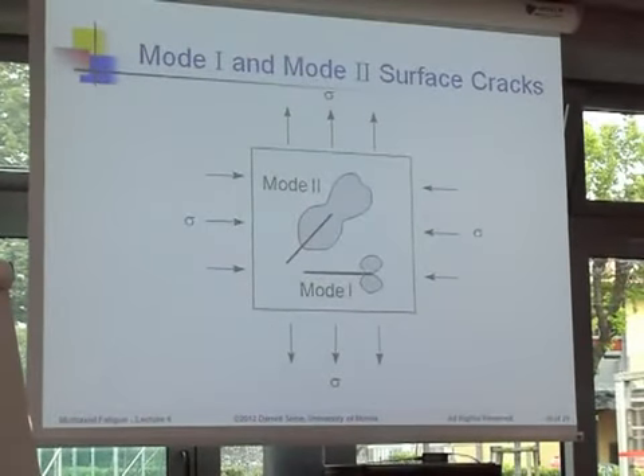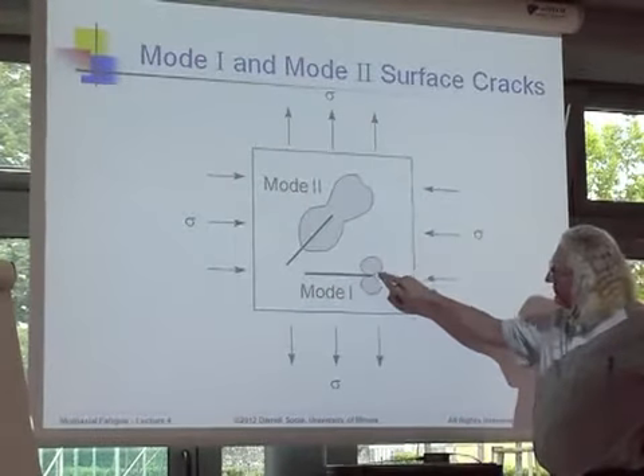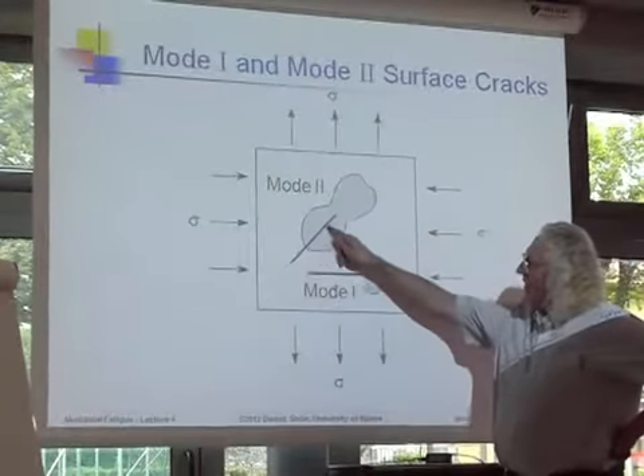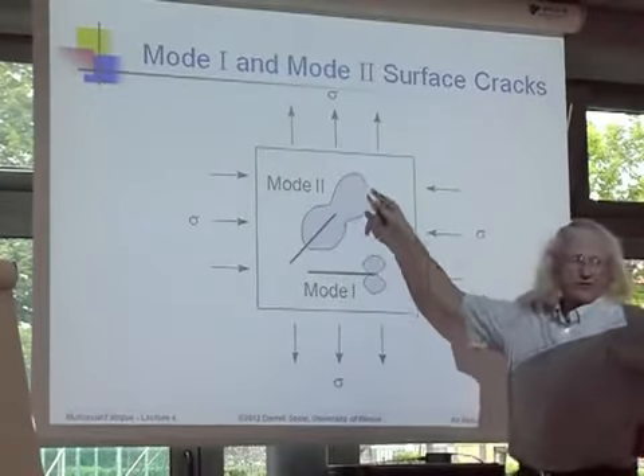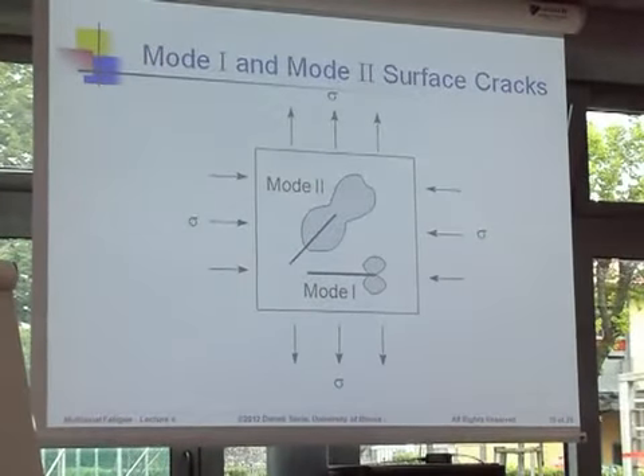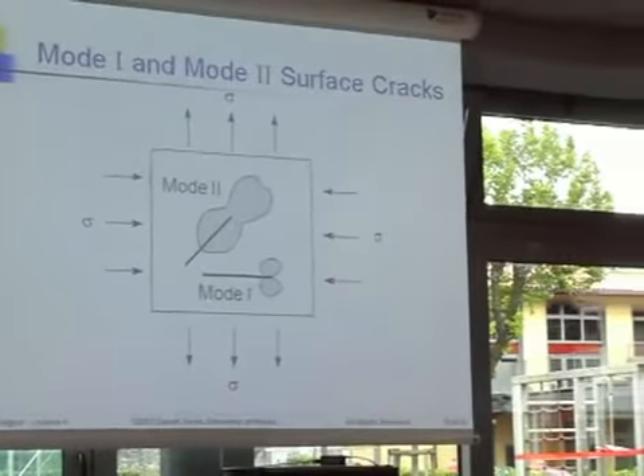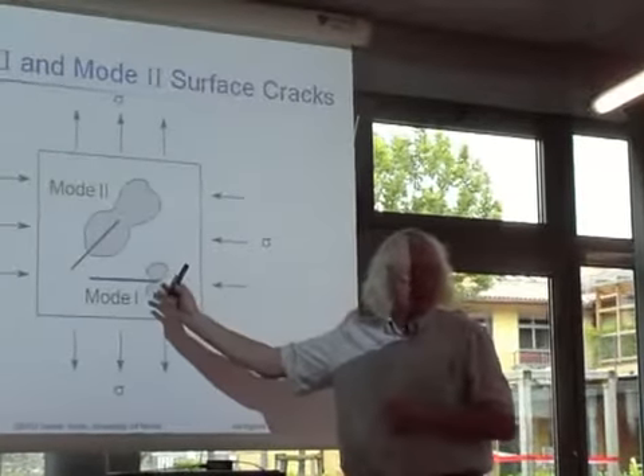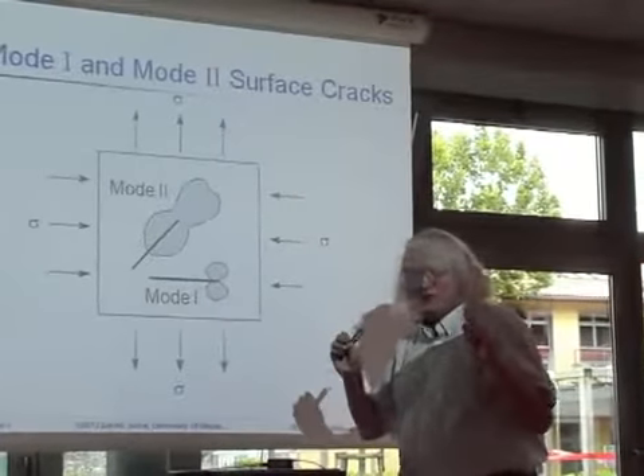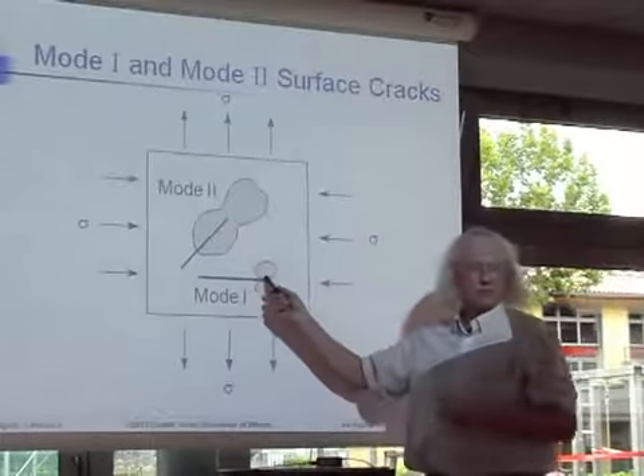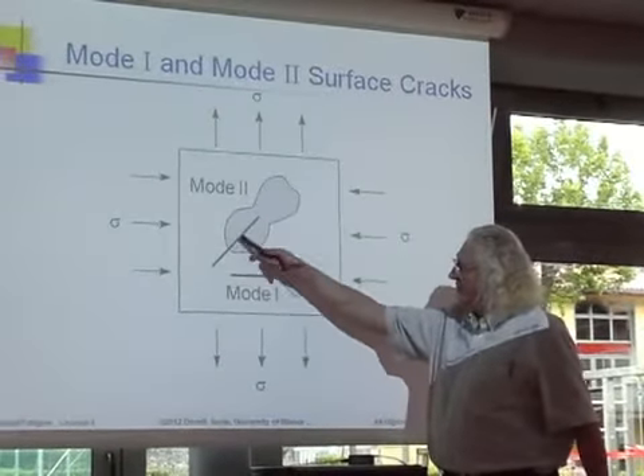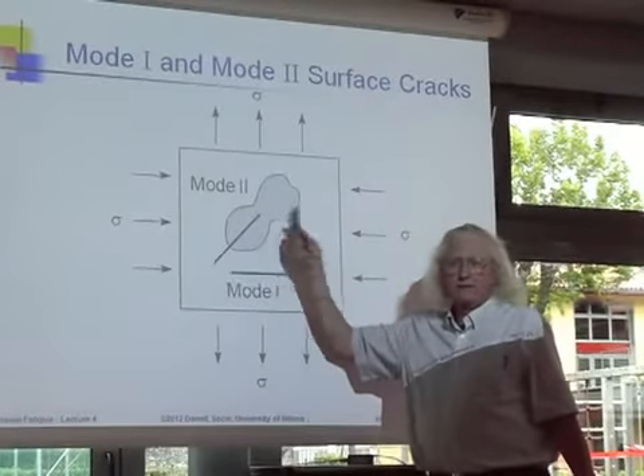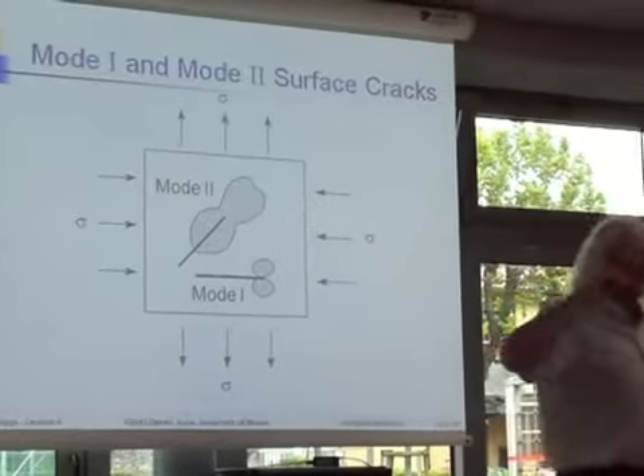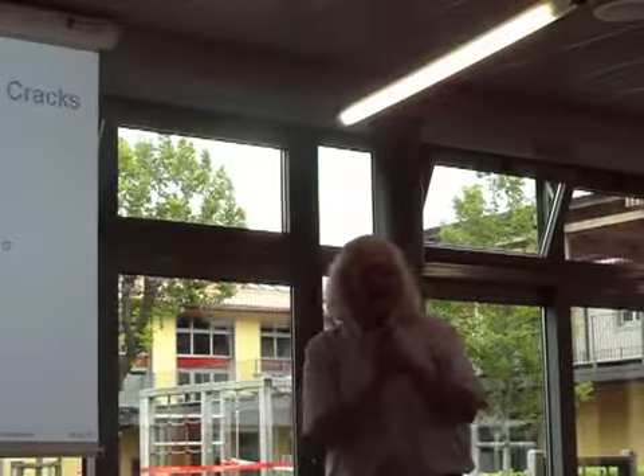Right? So here's that picture, and here's what happens for mode 1, just by introducing the shear loads, and here's the plastic zone, and here's another crack off at 45 degrees, and here's the plastic zone under the same stress system. So if you have a mode 2 sliding displacement, the plastic zones are huge. They are very, very big compared to the corresponding mode 1 plastic zone. And a material can choose how it wants to fail, and we know from our experience it always changes from this to this. Right? If I really have this crack in the structure, this crack is always going to change from trying to grow in mode 2 into mode 1. Maybe the natural world wants to have the lowest energy. So why not pick this other mode that doesn't require so much plasticity? Maybe this is the reason that these torsion cracks always turn. I'm not sure. So this is the mechanics of it.